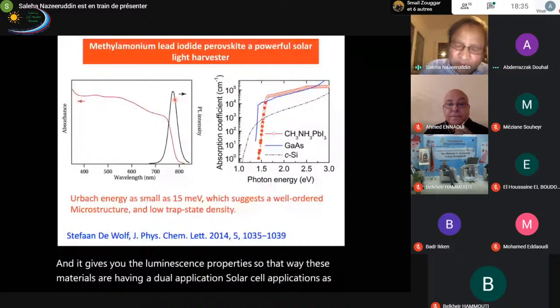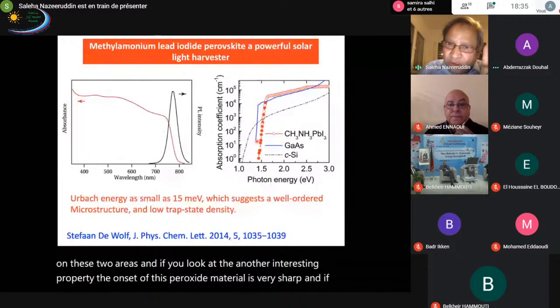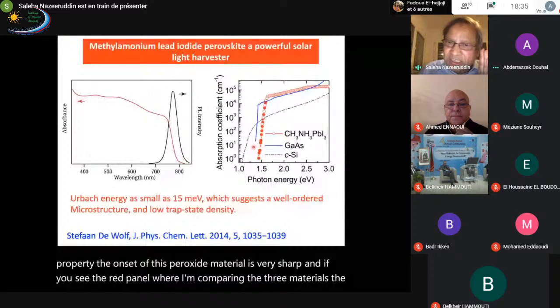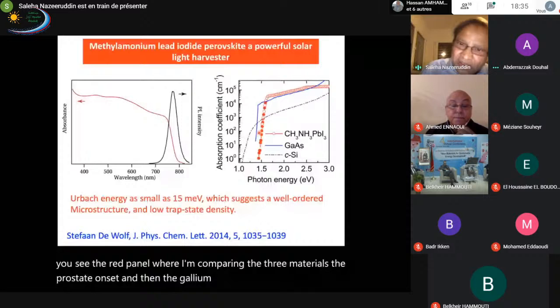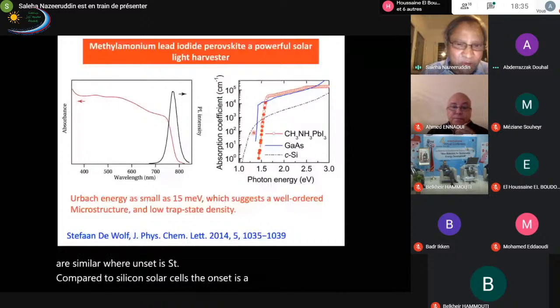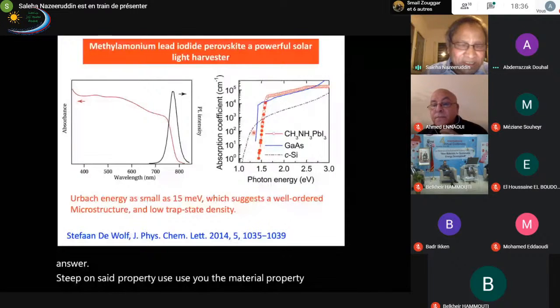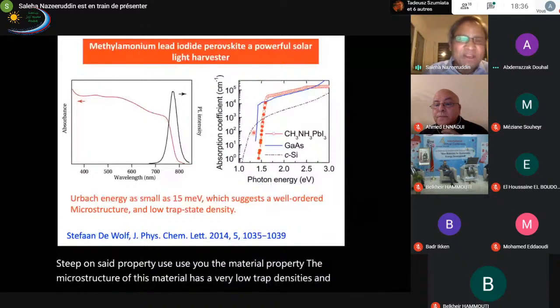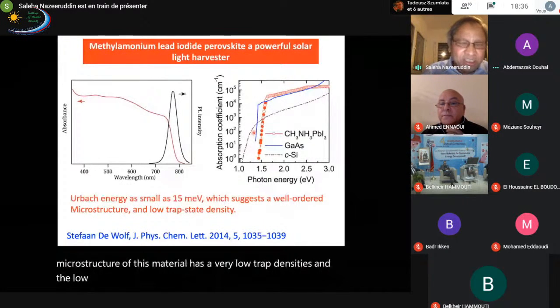Another interesting property is that the onset of this perovskite material is very sharp. In the red panel, where I'm comparing the three materials, the perovskite onset and the gallium arsenide onset are similar and steep, compared to silicon solar cells, where the onset is very sluggish. This steep onset reflects the material property: the microstructure has very low trap densities, the result of a self-assembly of these 3D materials, and that allows you to extract carriers at the interface.